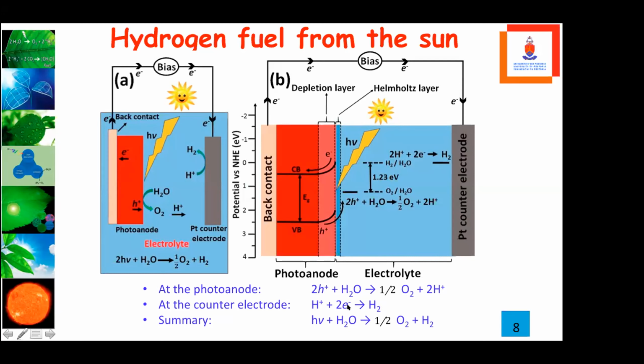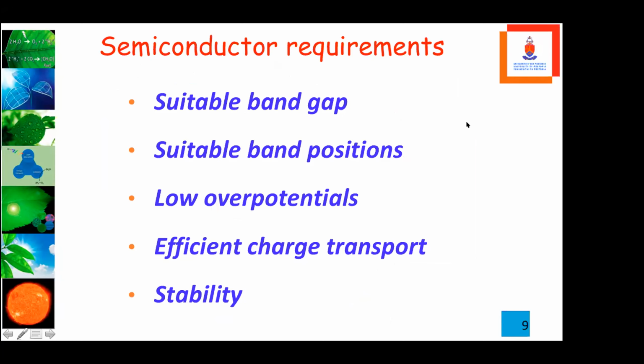We take energy and we apply it into water using the device that comes from a semiconductor and a platinum electrode, and you produce oxygen and hydrogen. What you are going to do is oxygen, you throw it in the atmosphere, you reduce the amount of carbon dioxide that is already destroying our environment, and you collect hydrogen for your transport issues. So our material that we are using in my lab is hematite for photoelectrochemical water splitting.